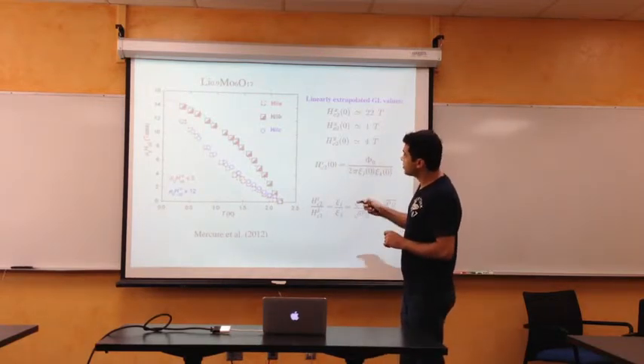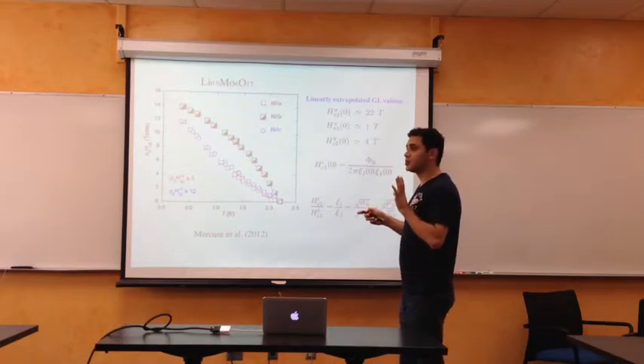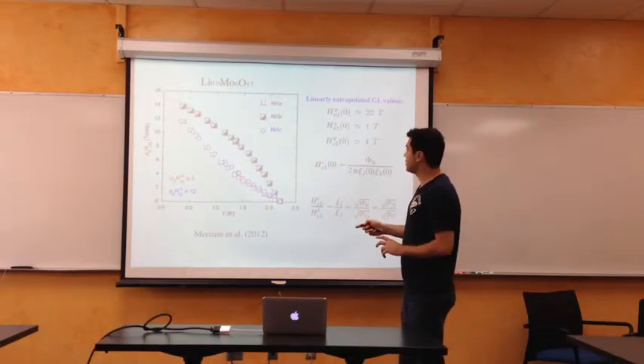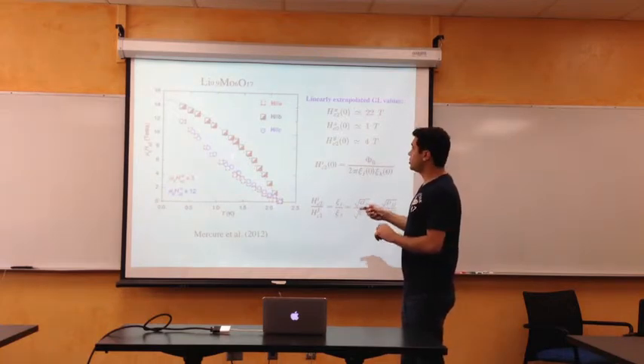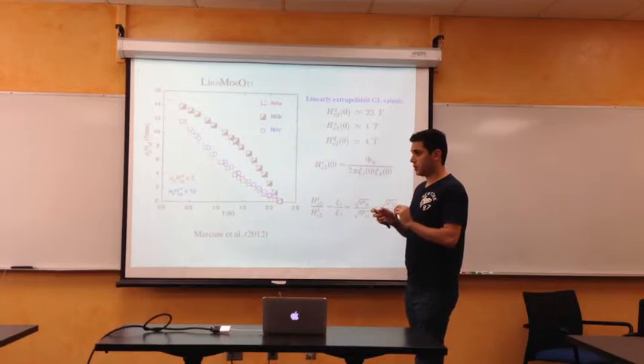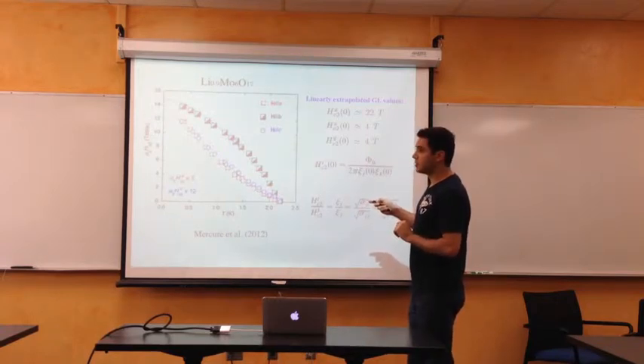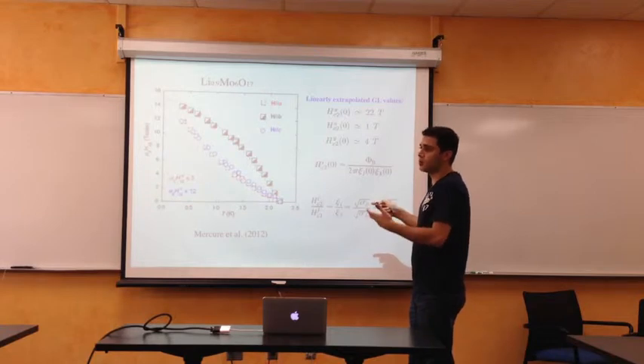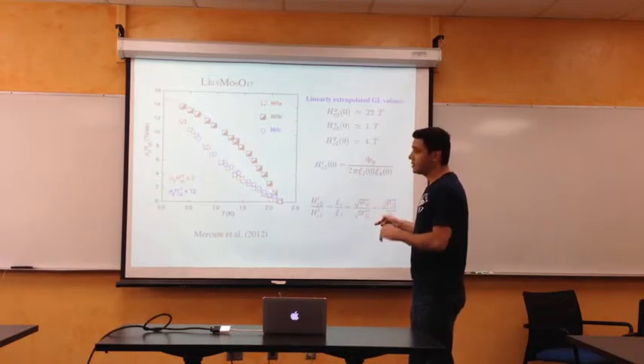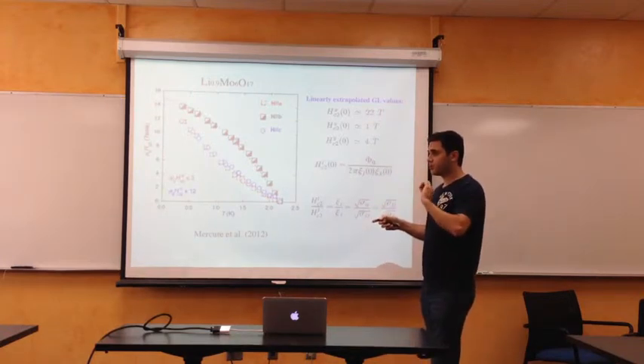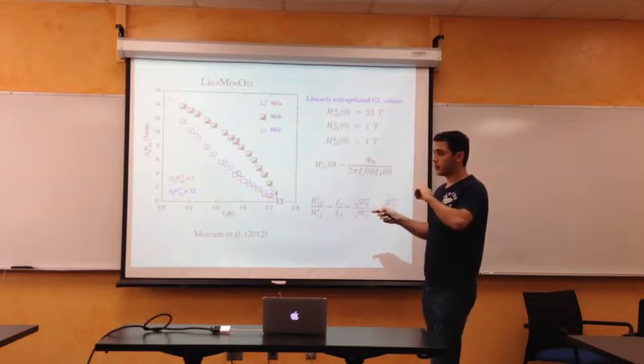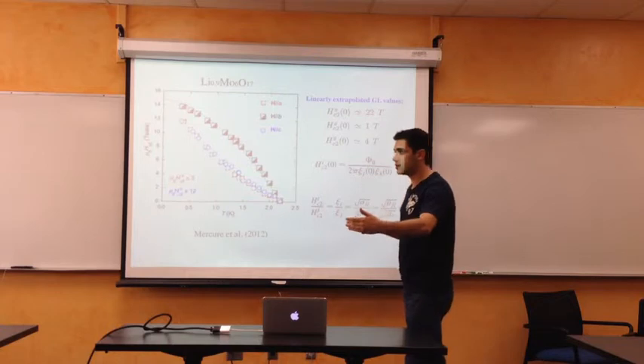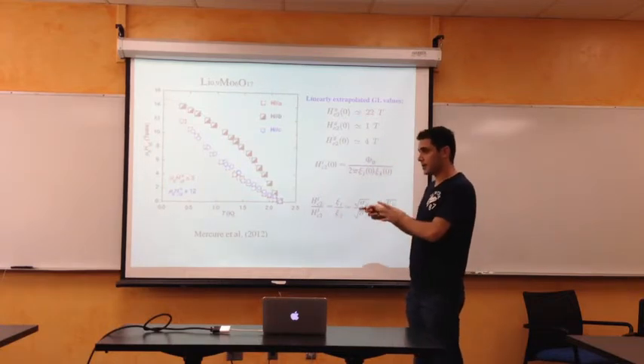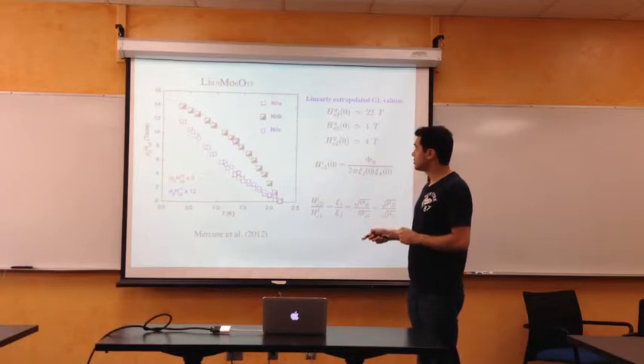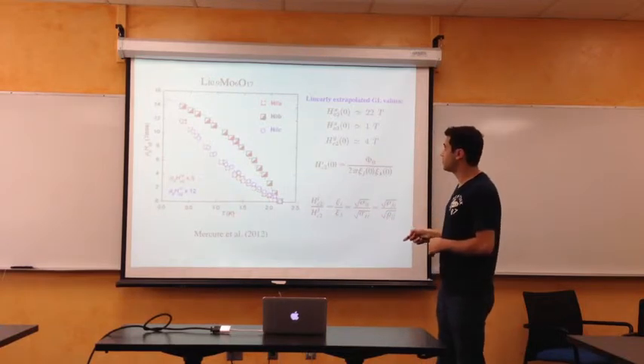Yes, as a function of temperature. So the y-axis is the externally applied magnetic field on this crystal versus the temperature at which superconductivity is destroyed. Above this curve, you can think of this as being the resistive state, in fact a normal metal, and below this curve you have superconductivity. This curve is the boundary at which superconductivity transitions, so it gives us the transition field to go from superconducting to a normal state. This value is in Teslas, this is in Kelvin.